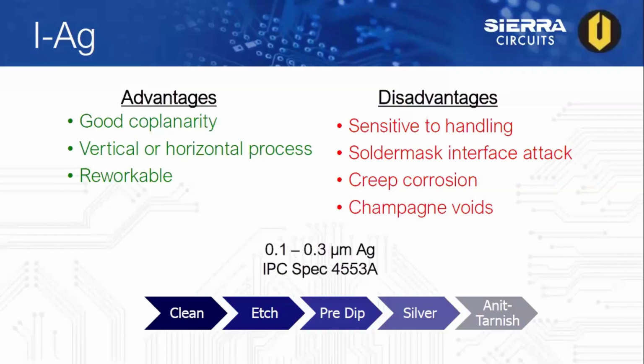Now a quick overview on the process for silver immersion. We start with cleaner, then move into an etch, go into the pre-dip, and then plate with silver immersion, and lastly apply an anti-tarnish coating. The specification for silver immersion is IPC 4553A, and per the specification we want to make sure we're between 0.1 to 0.3 microns of silver thickness.